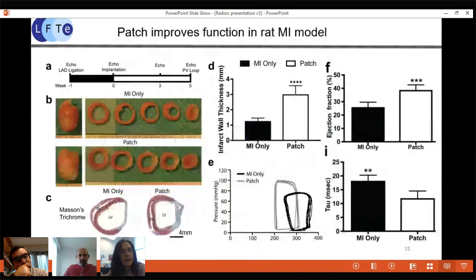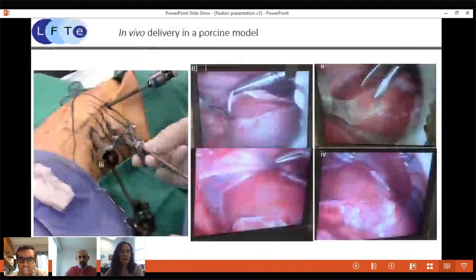The next important question was, does this biomaterial with cells improve the function of the heart after myocardial infarction? In collaboration with the lab of Dr. Ren-Ke Li at Toronto General Hospital, we were able to place this patch on, and we demonstrated that the infarct wall thickness was increased upon patch implantation. Ejection fraction was also increased, and diastolic properties such as relaxation were also improved, tau for relaxation time constant. So this tells us that the patch, through its own biomechanical properties, was able to improve function of the infarcted heart without inhibiting its relaxation.